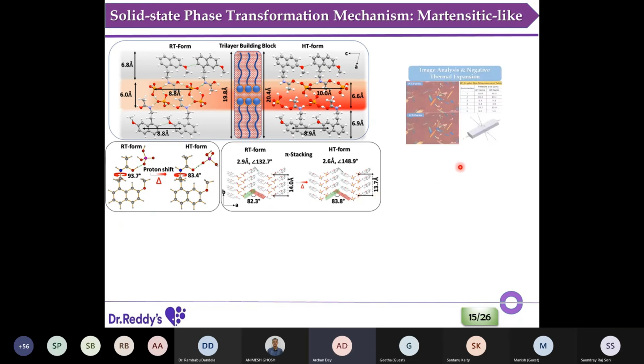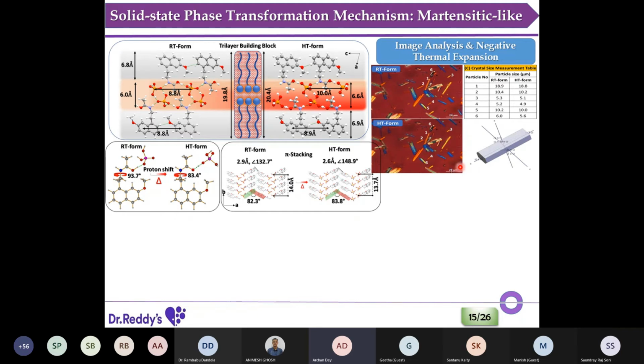This is nicely verified by image analysis of the hot stage microscopy images. First we simulated the crystal morphology of the material, and here we can see that our B axis is the long axis. Accordingly we measured the crystal, with no interference, and nicely we can see that a certain contraction happens. So it's called negative thermal expansion. The proposed mechanism is strongly verified by the experimental evidence also.